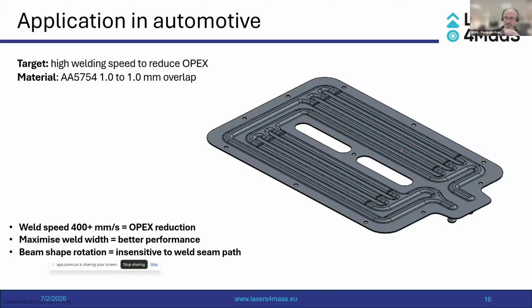Now, just very quickly, I want to show you one of those applications in the automotive sector. This is the mock-up of the battery cooler. This is a pretty interesting application because currently the way this is joined together is brazing in a furnace. And as you can expect, being a furnace operation, it is very high energy intensive, and also a relatively slow process. So that is our benchmark. We want to replace the brazing with a laser welding operation. And in order to meet the cycle time, we have to weld at least 400 millimeters per second as a bare minimum, with a target value of 800 millimeters per